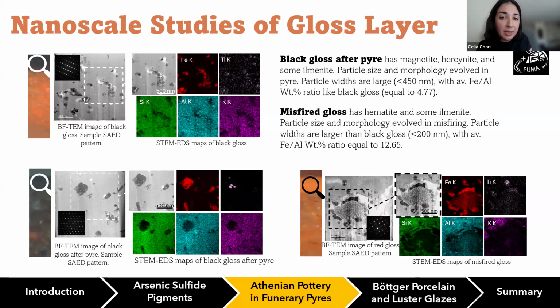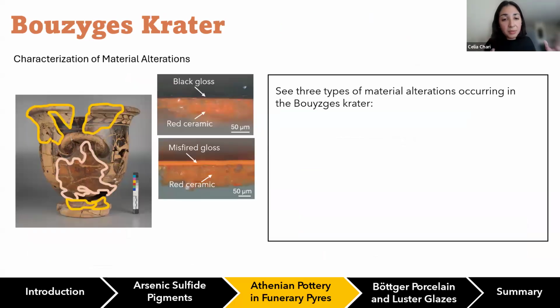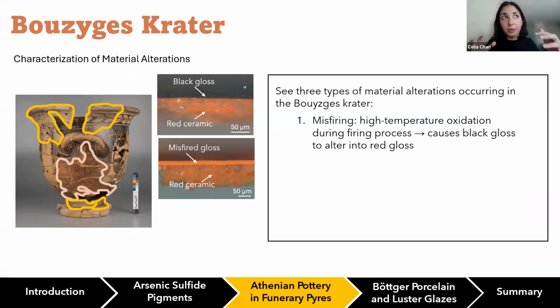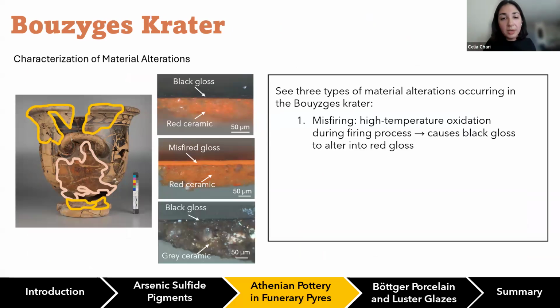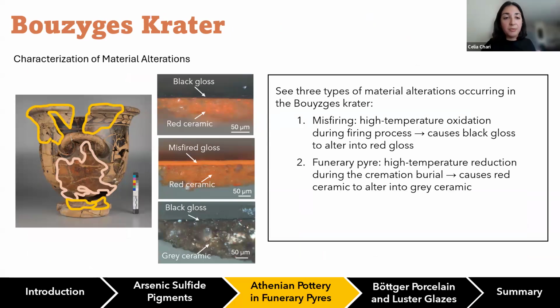grow larger. And our analyses of the elemental compositions supported what we had seen previously, that there is a lot of iron oxide directly from hematite within the red gloss, and that it's much higher than what we saw with the other black glosses. So there are two different things happening. There's the misfiring from the actual production of the crater. There's the exposure to the pyre from how this crater was then incorporated into a funerary ritual.